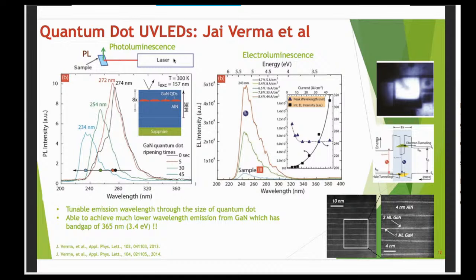So what we would see when we shone a laser on this, as we decreased the size of the quantum dots, the wavelength of emission from these structures was decreasing. It went all the way from 274 nanometers to 234 nanometers. That is what we expect, right? If you decrease the size of this well, this energy level should go up. And that was a clear indication that we were getting quantum mechanical effect in these structures that we were growing.